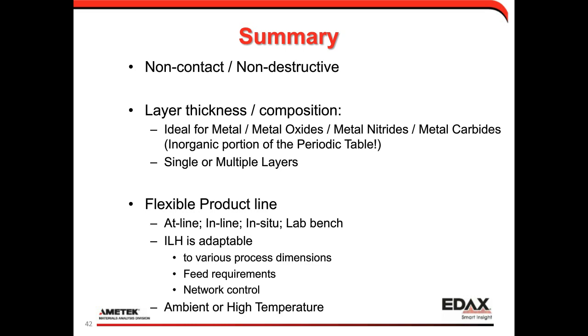The question is, we have a continuous web with a light metal coating. Can your system be adapted for this application where we look at zinc for the main part along with gold and silver at the edges? Yeah, that can be done. As I said, we have a measuring head that can move across the width of a sample, and it's very good for measuring zinc, gold, and silver. These are all elements which will generate X-ray signals, which can be measured by XRF.